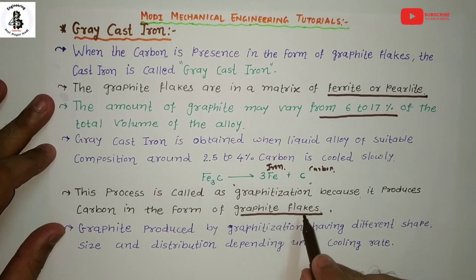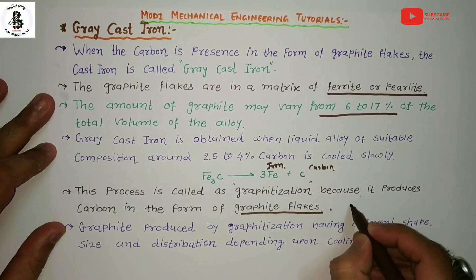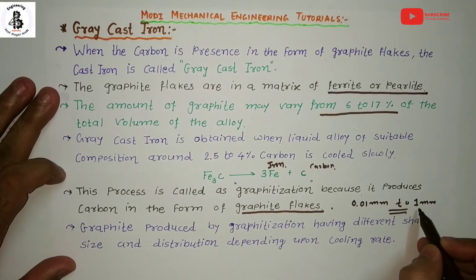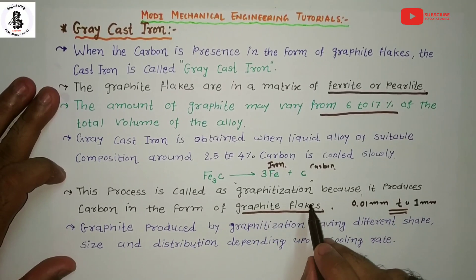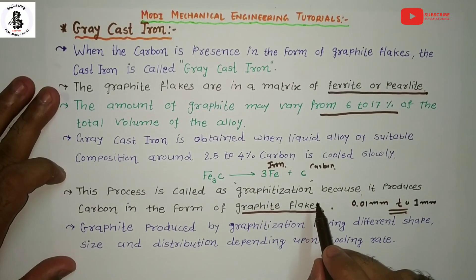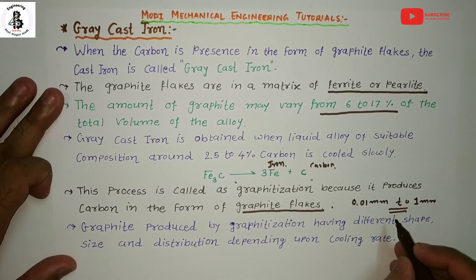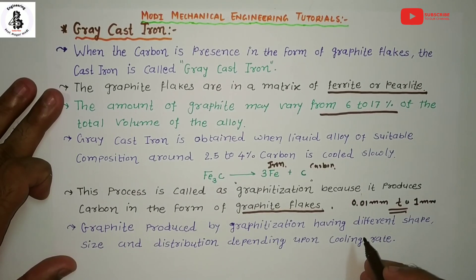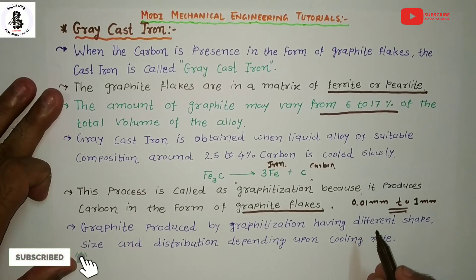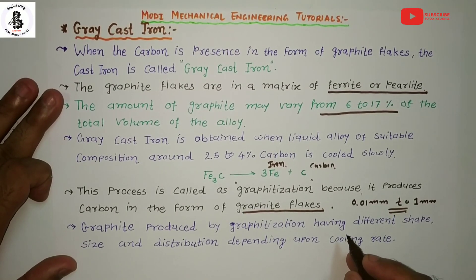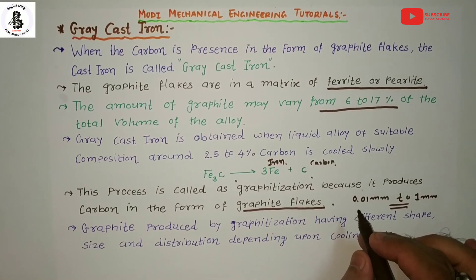The graphite flake length from the graphitization process generally varies from 0.01 mm to 1 mm. Large graphite flakes interrupt the pearlite matrix, causing reductions in strength and ductility. For better properties, smaller flakes are preferred as they cause less damage to the structure. Slow cooling of hypo-eutectic gray cast iron results in coarse flakes; increasing carbon and silicon content also increases graphite flakes and decreases casting strength.